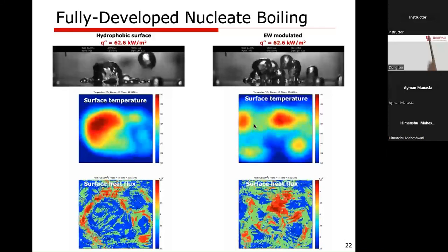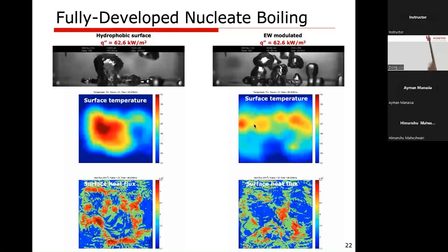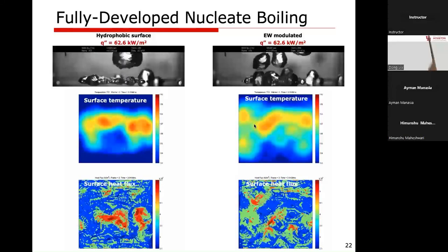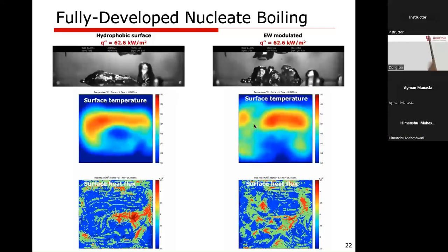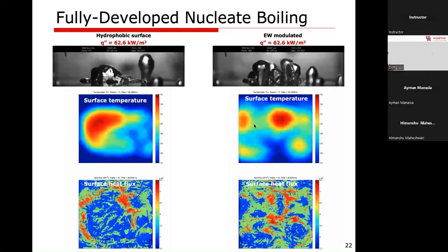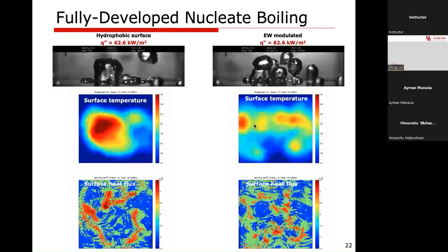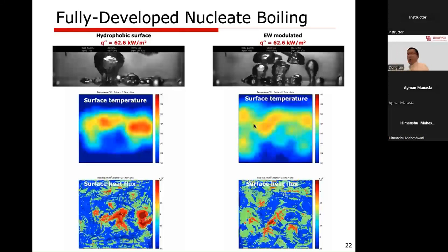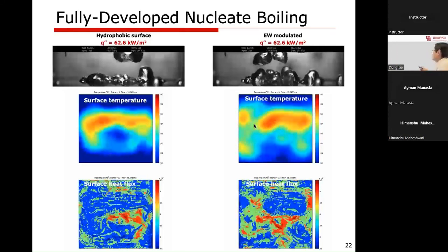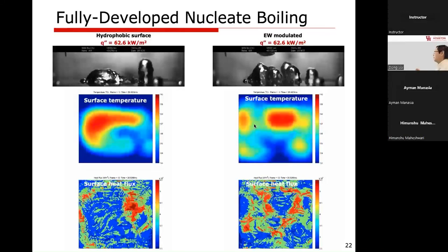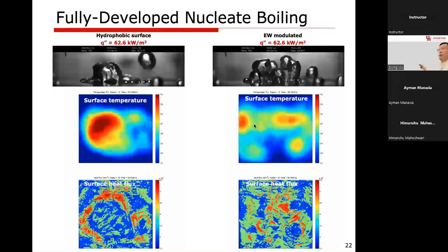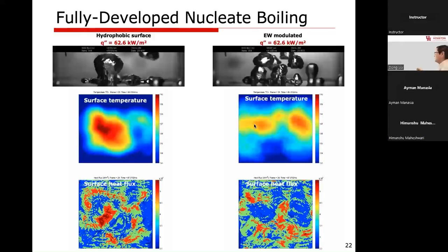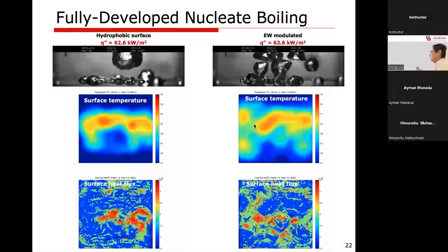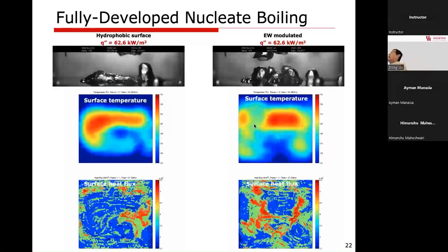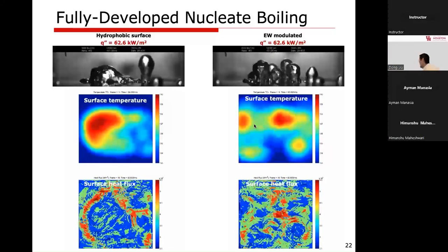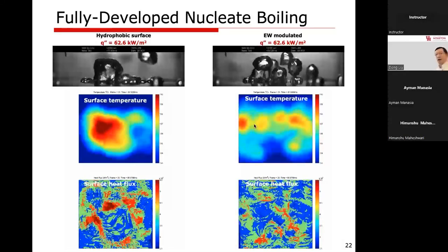Now we also extract the heat flux from the image. So you can see the red part of the high flux region. Now the blue color region is a region where the heat flux is low. Therefore, there's not much heat transfer occurring because that region is being covered by the dry vapor. Now with electrowetting, you see at the same condition, you no longer have a big bubble hovering over the surface. Instead, you start to see the reappearance of the individual bubbles. So you can see, there's no more big hotspot. Instead, you have smaller, separate hotspots. Right? So that is good for heat transfer. Also, overall, the heat flux of the surface is enhanced.